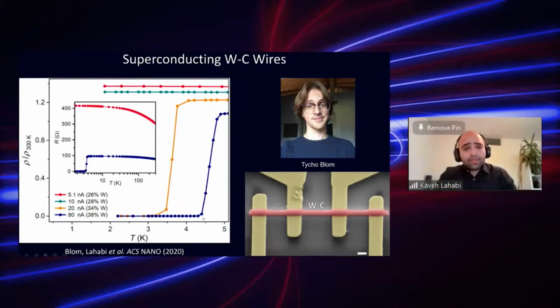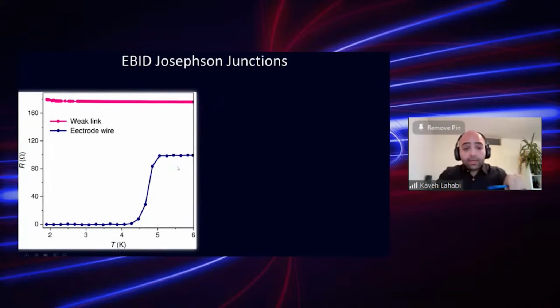But more importantly, we noticed that by adjusting the beam parameters, we can tune the electrical properties of this tungsten carbide. So, for instance, if I scan the electron beam slowly, I would make superconducting tungsten carbide. But if I do a faster scan, then I make metallic but non-superconducting tungsten carbide. And this provided us with the means to make our Josephson devices. So this is how we did it.